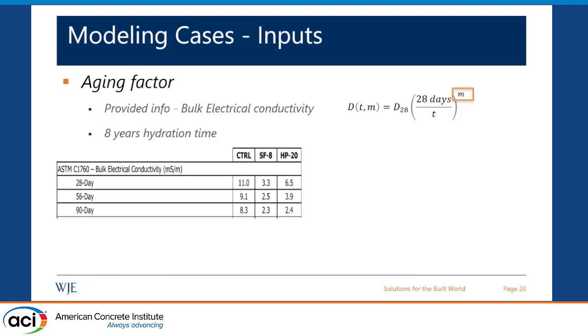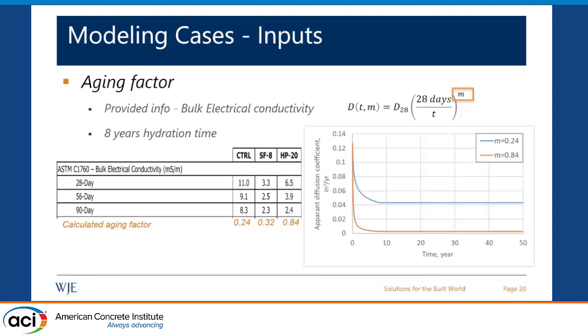any electrical testing is actually affected highly by the chemistry of the pore solution as well, which could potentially give you misleading results, especially with some of the supplementary cementitious material. So you have to be careful considering the lab test results when you're performing your service life analysis. So based on the bulk electrical conductivity, this was the calculated aging factor, similar to the numbers that Brad mentioned earlier.